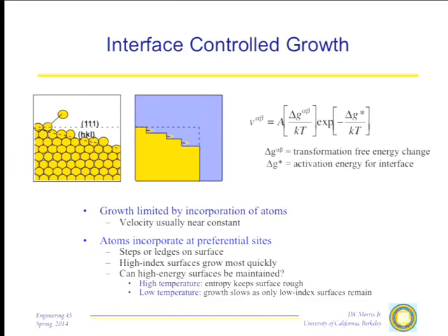If, on the other hand, the solid we're talking about has a very anisotropic surface energy, or if we're talking about low temperature where the surface isn't enough entropy to make the surface diffuse, then our surfaces tend to be very regular. And then the atoms can only incorporate at the edges or corners of rather well-developed close-packed planes. And this is true of the growth of many compound crystals, of many complex crystals where we're crystallizing organics or things like that. We have this situation.